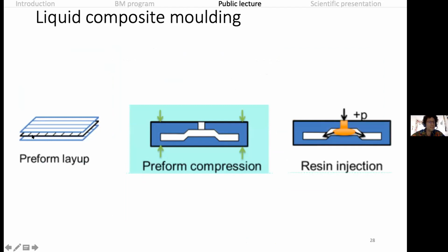So the idea here is that you take your dry textiles, and you lay them up. So you do your stack of textile. That gives you your preform, your dry preform. You put the dry preform inside a mold that you close down, and then you inject the resin, so the plastic, inside the mold, and hopefully the resin is going to flow inside the porous material and fill the mold and make your part, your mixture of fibers and resin. This is a typical composite manufacturing process.